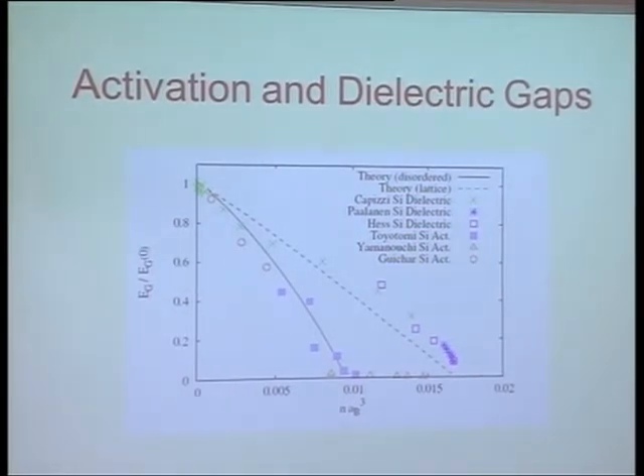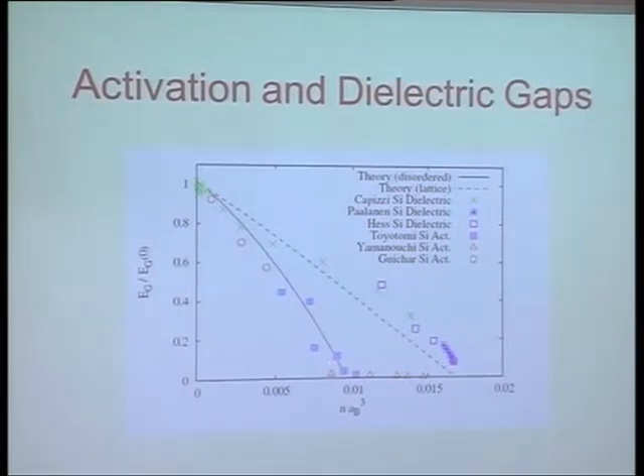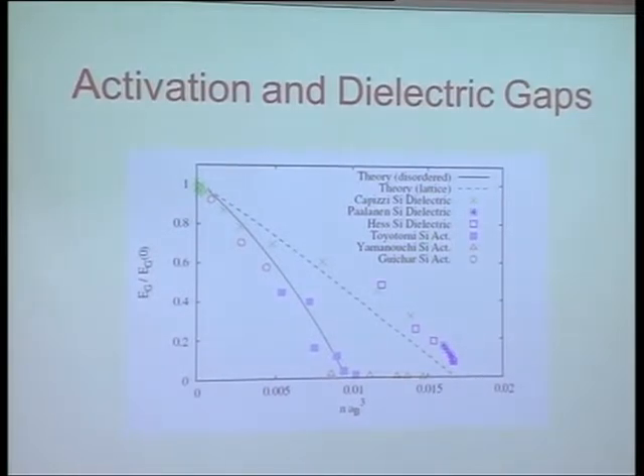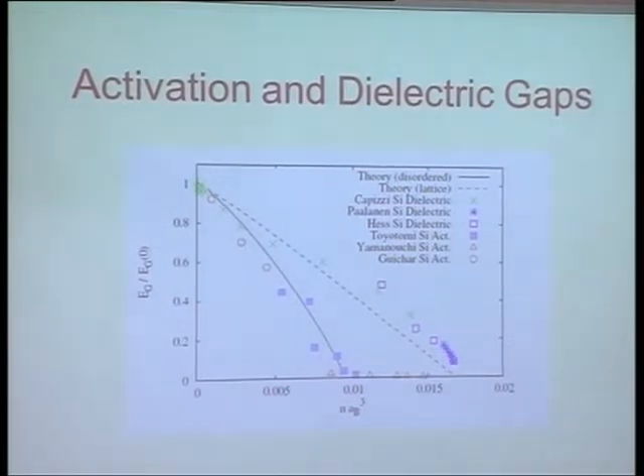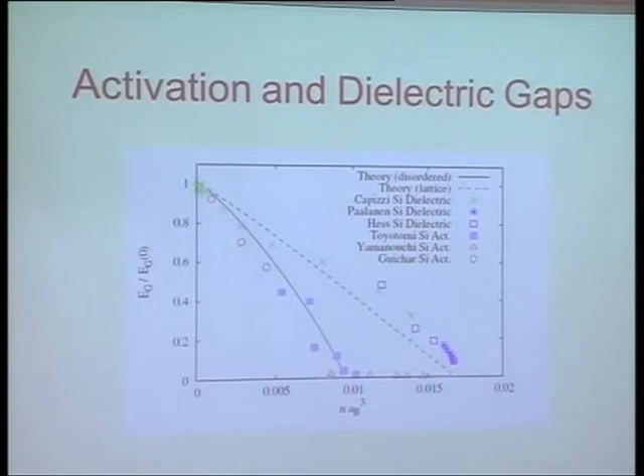In any case, if you look at the experiment — something that has not been recognized, I think, to date — it looks like it's going to become metallic, then suddenly hangs up, and for another factor of two in density, it stays insulating. So there are clearly two regimes of insulating behavior. This is what I would call a Hubbard insulator with a large activation energy, and the other is more like an Anderson-Efros-Shklovskii-Coulomb gap insulator.